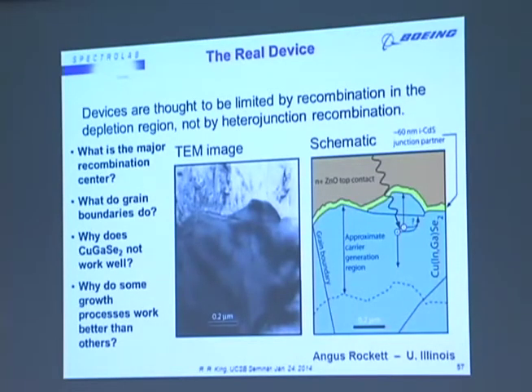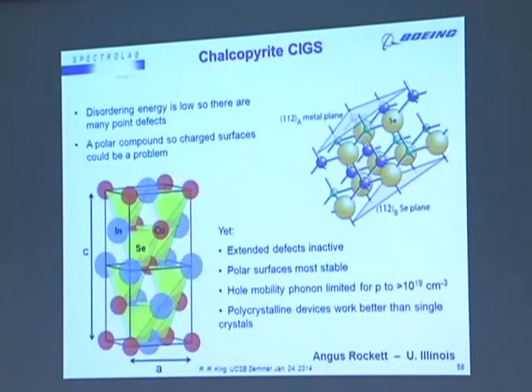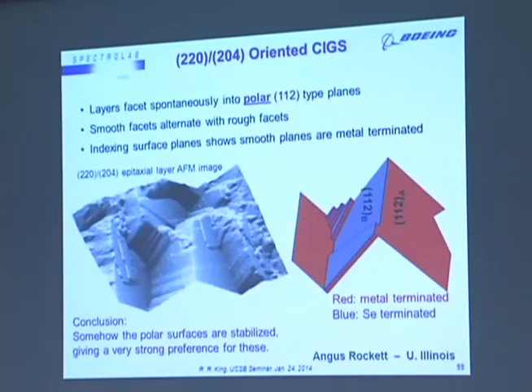So some questions here are, what is the major recombination center? I think maybe I'll skip over some of this work in the interest of time, except to say that a very interesting observation by Angus Rockett at University of Illinois is that these layers facet spontaneously into polar 112 type planes, which is very interesting, that the polar planes are stabilized and preferred.